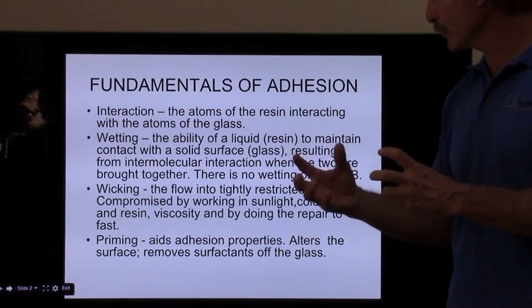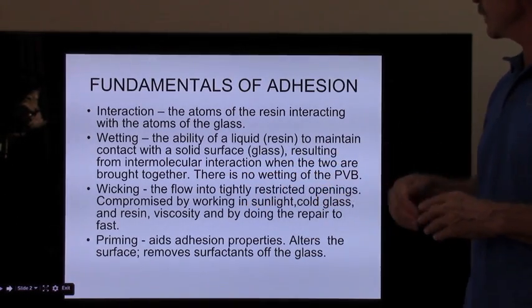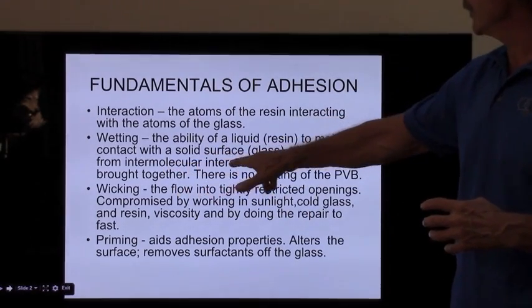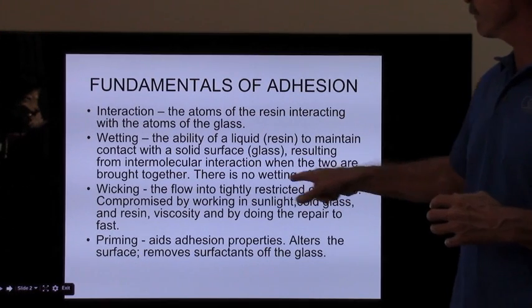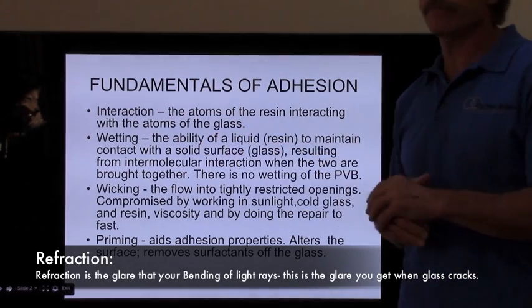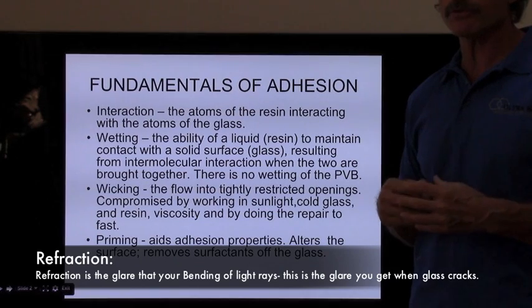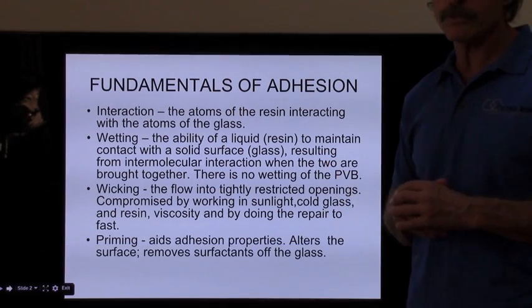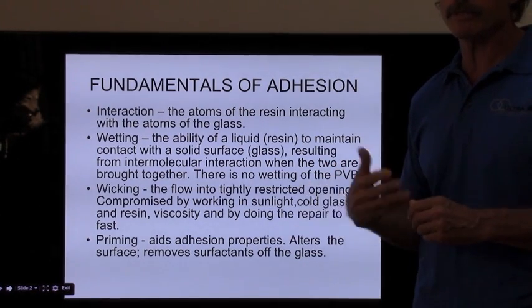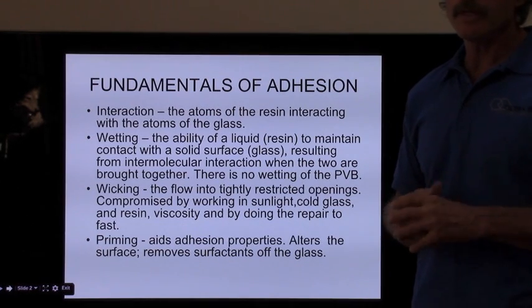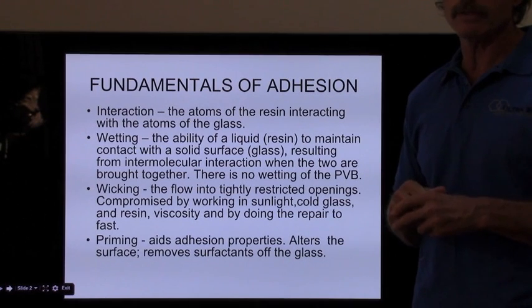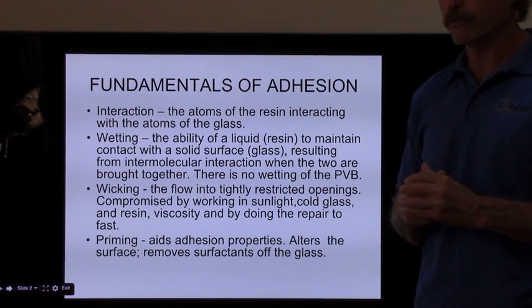So when it is more attracted to one surface than the other surface, there's going to be a problem, because PVB is also a low energy surface like resin. They're so close together that there is no intermolecular interaction between the resin and the PVB. So you have to bond to the PVB or you're going to have refraction. And I'll address how you bond to the PVB, because you have to. You bond to the glass so that the crack doesn't spread further and you restore the structural integrity. But if you don't bond to the PVB, your repair is going to look like it's not repaired, because there's going to be a separation between the resin and the PVB, which will refract, it will glare, and that is unacceptable. It would fail the standard, the repair of laminated autoglass standard criteria.